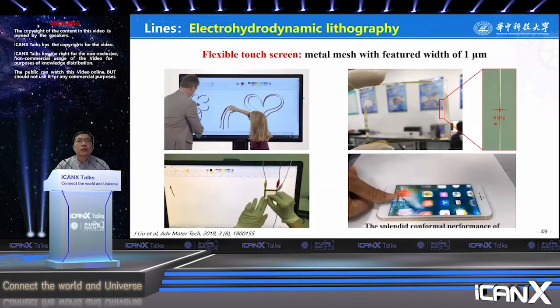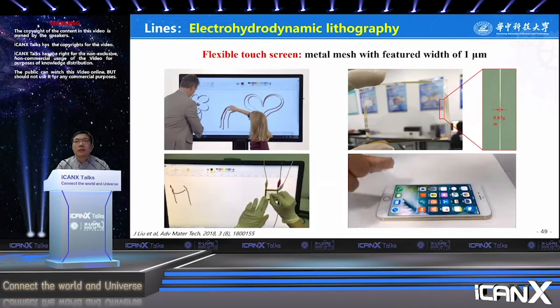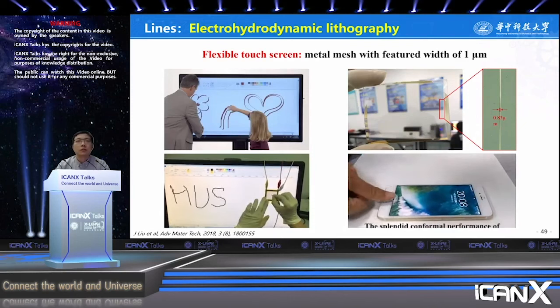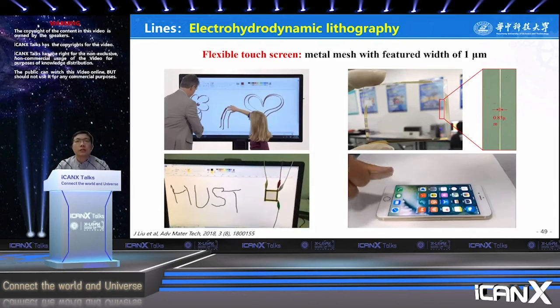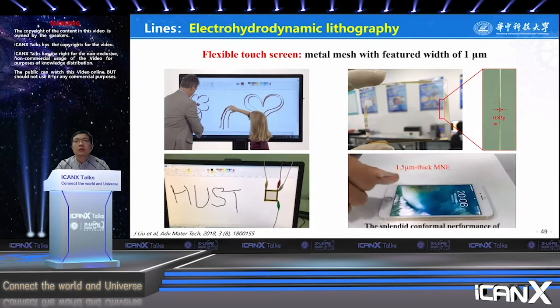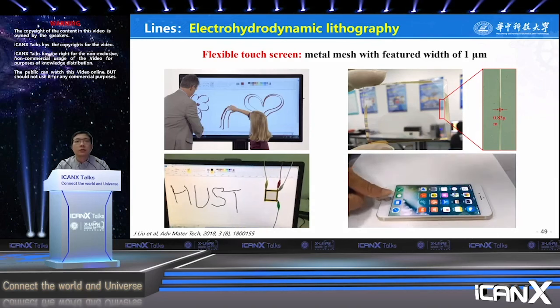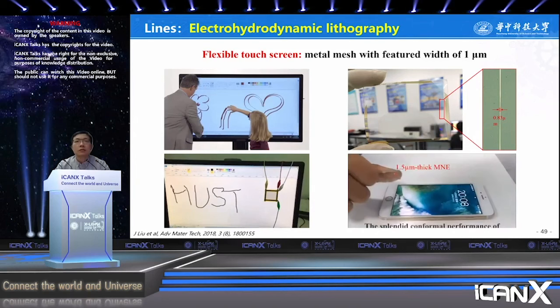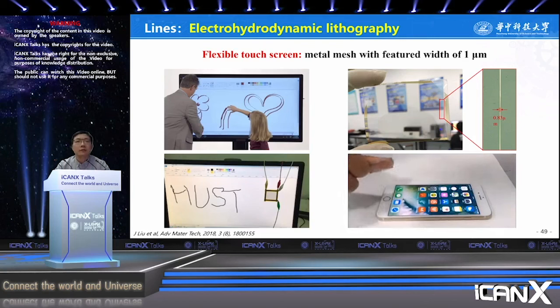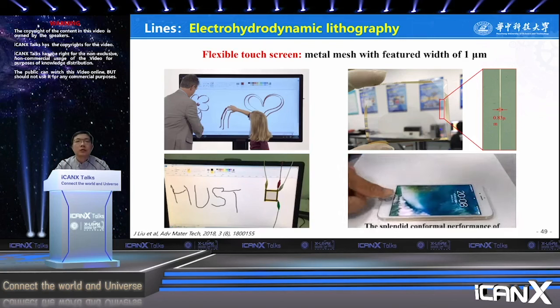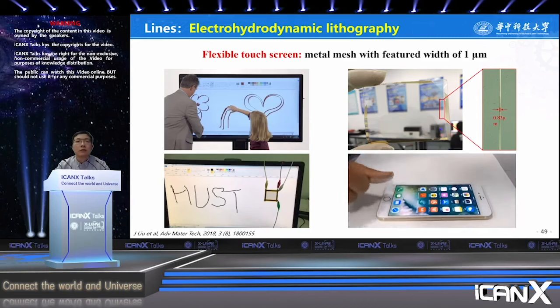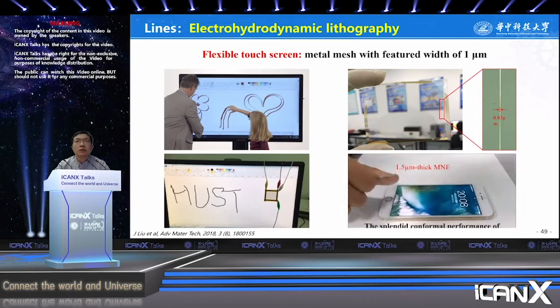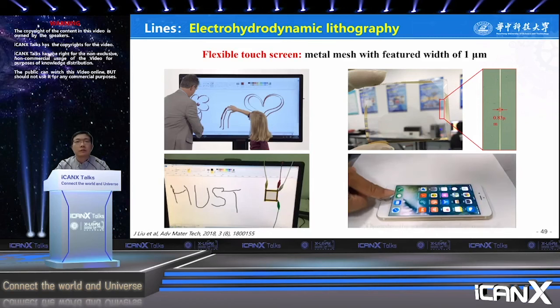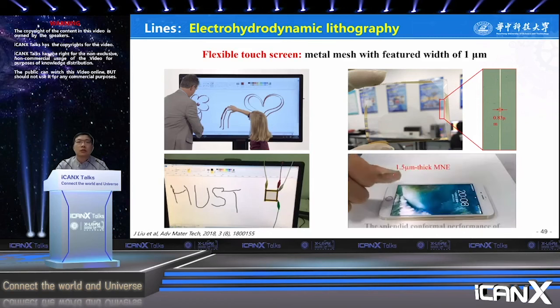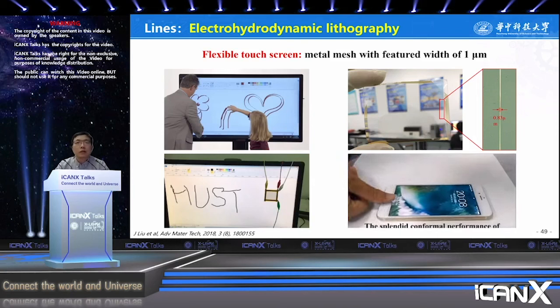In the previous page, the place that is covered by the printed photoresist needs to be removed. Inversely, in this page, the place that is not covered by the printed photoresist needs to be removed. For example, we use this method to fabricate a transparent metal mesh for flexible touch screen. Firstly, the substrate is coated by thin metal film, and then the mask is printed on the film via EHD direct writing. Thirdly, the object is put into etching solution. Finally, we removed